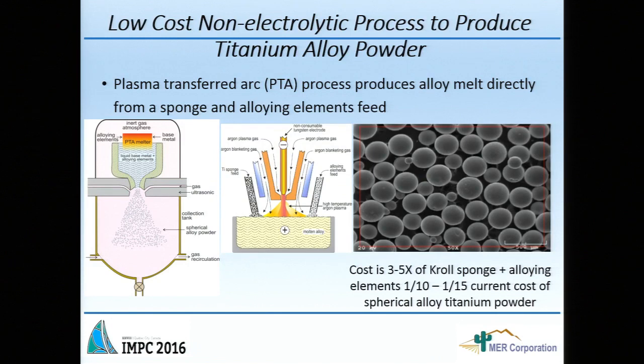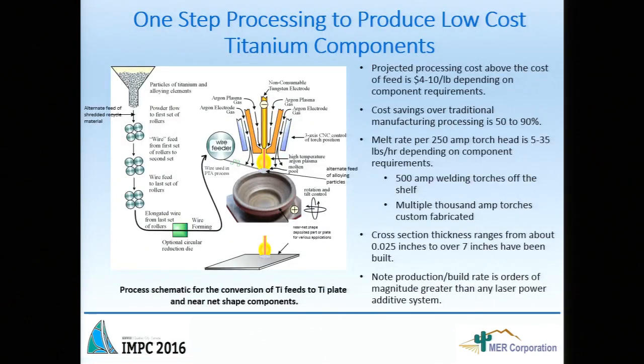As I mentioned to you, we have a plasma arc process that we produce components, and we can actually take metal and go through the plasma, and if you use a non-electrolytic process, you can spheroidize it. You can produce spherical titanium. So we can start with the sponge directly and go into the plasma and produce powder.